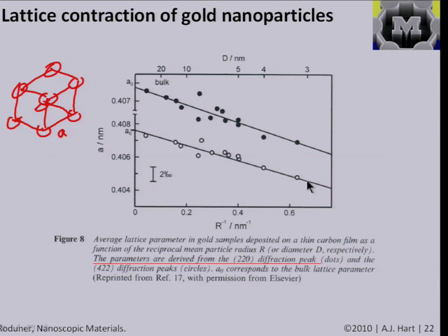And this also shows that using diffraction, or using the interaction of X-rays with the material, you can get a pretty precise measure of the spacing. And this is simply because as the particle gets smaller, this is inverse dimensions, there's more pressure inside, and therefore you're physically squeezing the atoms closer together.